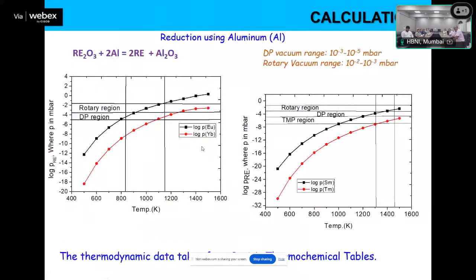And these are the plots. On the left side there is ytterbium and europium, and on the right side there is samarium and thulium. This is the log scale, log PRE. These are only theoretical calculations. Around 800 Kelvin, looking at this black one, europium cannot be done. But if you go to around 1200 Kelvin, the partial pressure comes under the rotary range. Rotary range means 10 to the power minus 3, basically vacuum. For new students, 10 to the power minus 3 means rotary vacuum, 10 to the power minus 4 to minus 5 you can say DP vacuum, diffusion pump vacuum, then turbomolecular TMP, and then titanium sublimation pump type of vacuum, high vacuum.